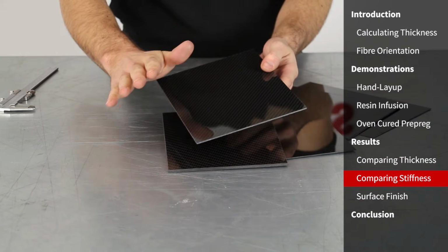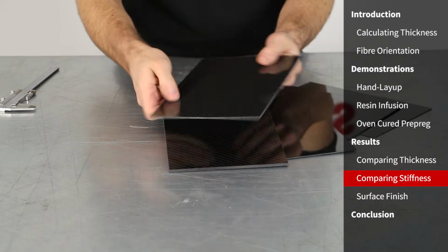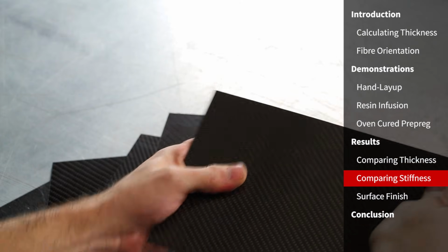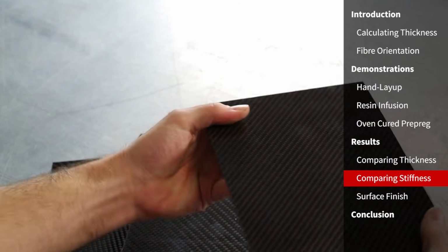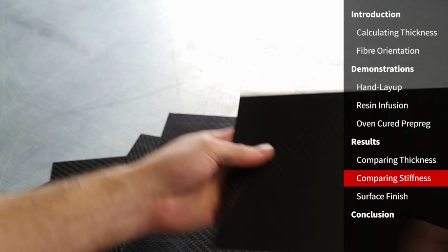And finally, the prepreg sheet. Again, we did multi-axial orientation of the fibres, so we had the 0-90 and ±45, which is giving us that same even distribution of strength.